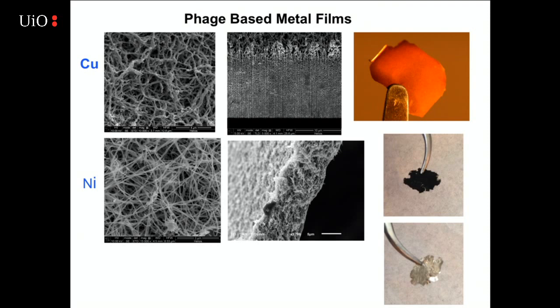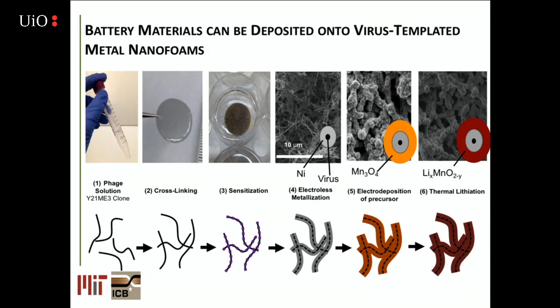My students went on and spent a lot of time building foams out of these. This is a copper-based foam and a nickel-based foam that are freestanding foams of these different kinds of materials. And then once we have these foams, making hydrogels, from hydrogels making foams, and then starting to coat them with other materials. So in this case, you have nickel nanofoams. On the outside, you have lithium manganese oxide based materials.